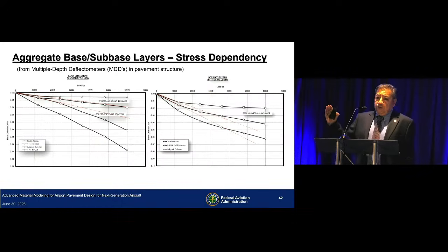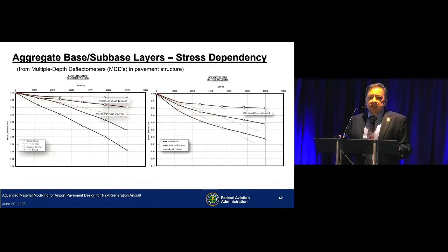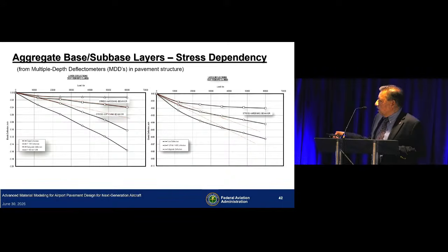So that was the asphalt material. How do aggregate material and subgrade soils behave? So what you're seeing in these charts is the measurements of deflection from multiple depth deflectometers. And one of the advantages of MDDs is you can look at deformation coming from each layer of the pavement structure. And what you see here is for medium strength subgrade. It's a clayey soil. So this is your total deflection. That shows kind of linear behavior. But when you start looking at the subgrade, it's showing stress softening. When you look at the aggregate materials, they're showing stress hardening behavior. So it's the combination of these two contradicting behaviors, stress hardening and stress softening, that results in almost linear behavior.